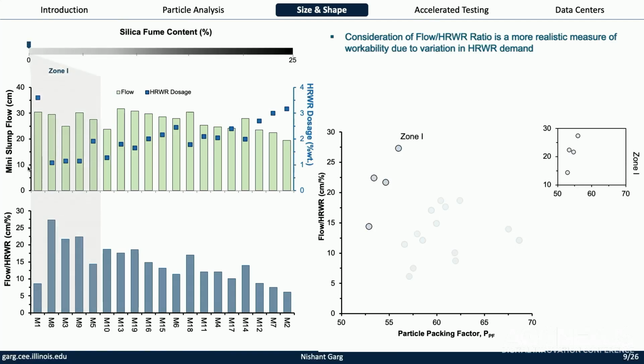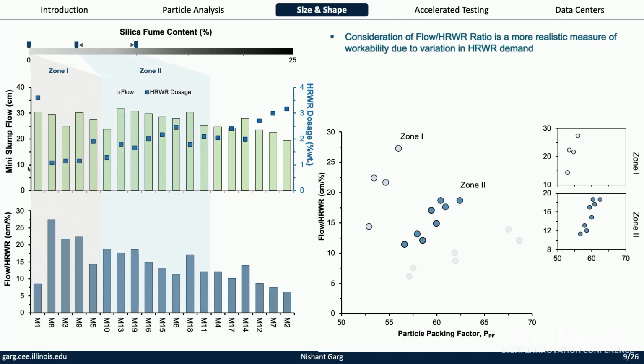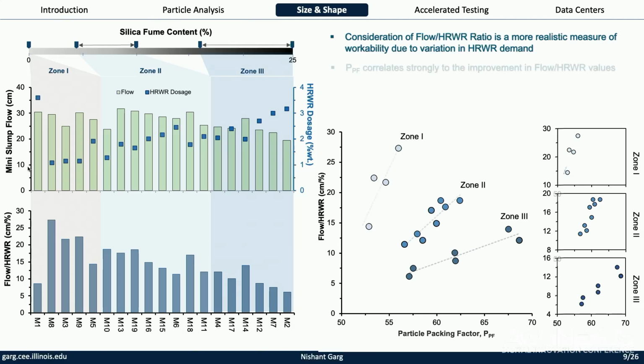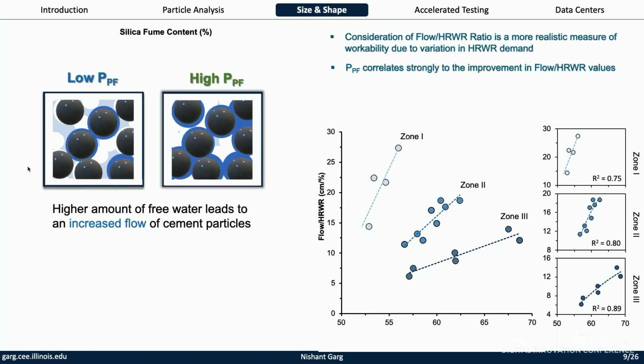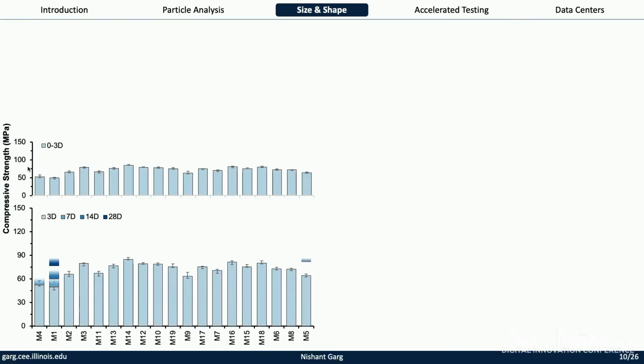But if we break them down, depending on the silica fume content, we decide 3 zones based on the dosage. It turns out there's actually 3 different zones where the correlation actually works, right? So across mixes, the data looks junk, but if you look at specific set of mixes based on the silica fume content, there's actually very nice correlations, right? So sometimes it looks like bad news, but you have to do a little bit more digging. What is happening is that the higher PPF value, you have now more free water, which allows better lubrication, better packing.